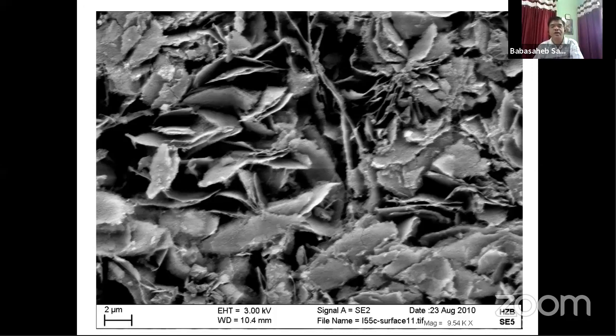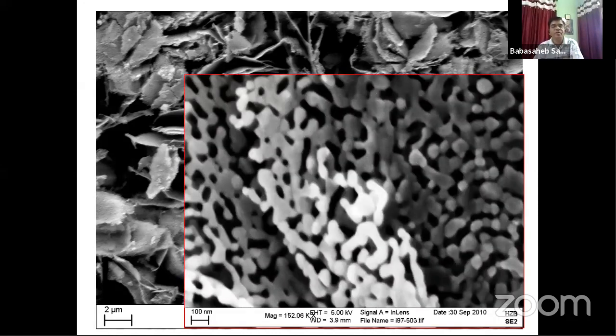So in order to get a clear insight, we took the high resolution SEM image, and here you can see the scale bar is 100 nanometer. With a very small scale bar, you can clearly see how these nanoparticles are internally connected to each other, and this has a very high surface area. This morphology is analogous to a cactus-like morphology. So you can say that this is zinc oxide with a cactus-like morphology, which has a very high surface area, which is the basic need for the dye-sensitized solar cell, on which you can coat a monolayer of the dye molecules on this wide band gap zinc oxide.